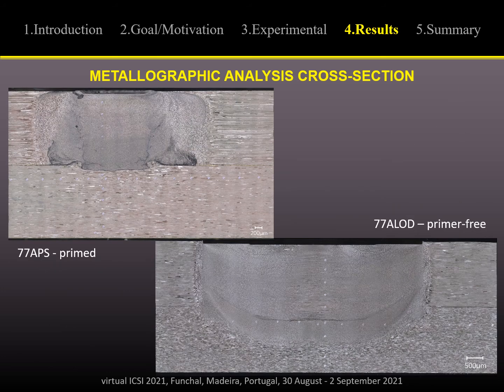Also, metallographic analysis performed on cross sections of primed and primer-free 7050-7050 configurations shows that there are differences in weld nugget appearance. You can see here the primed version. There are remnants of primer at the interface of both top and bottom sheet, and this weakens the joint, of course. Whilst in the case of the primer-free configuration, there is only a small ligament of sealant inside the nugget zone.